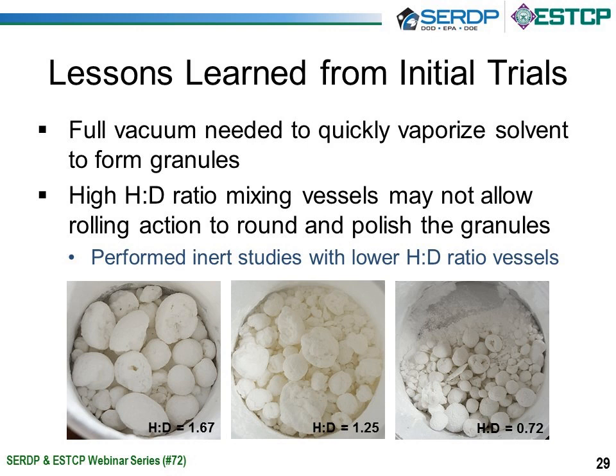However, we did notice that these high H-to-D ratio mixing vessels did not allow for the rolling action to round and polish the granules. So we decided to start doing some H-to-D ratio experiments, but we decided to first use inert materials, sugar, so that we wouldn't generate a lot of energetic waste during these optimization of the mixing vessel. What we did is we started cutting down the H-to-D ratio from 1.67 to 1.25 to 0.72.